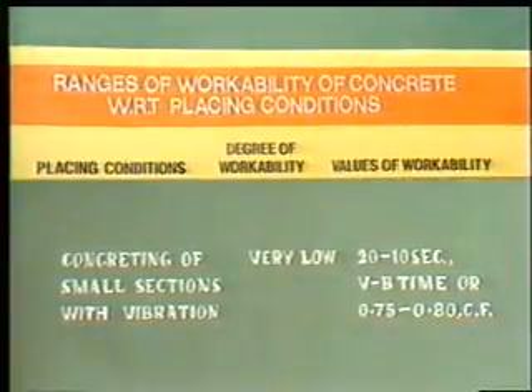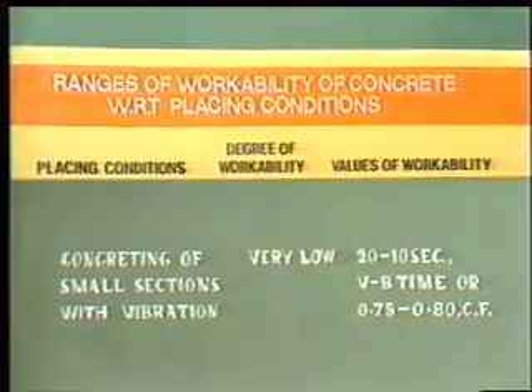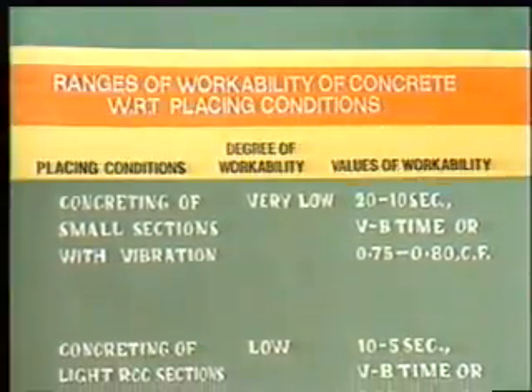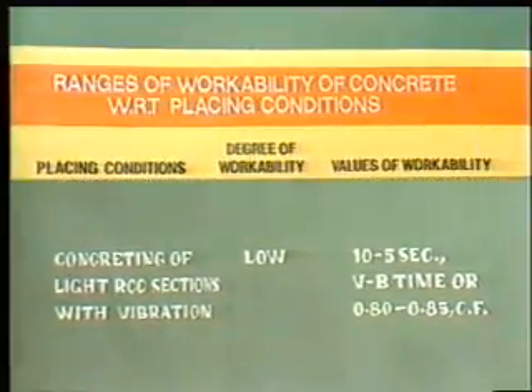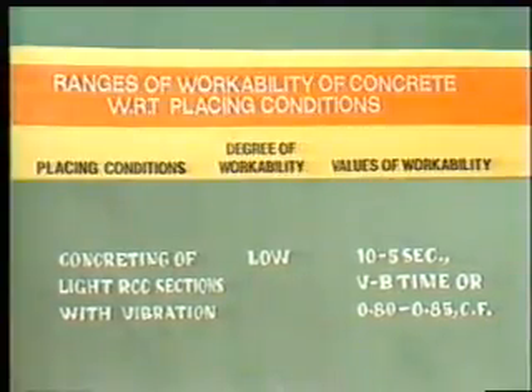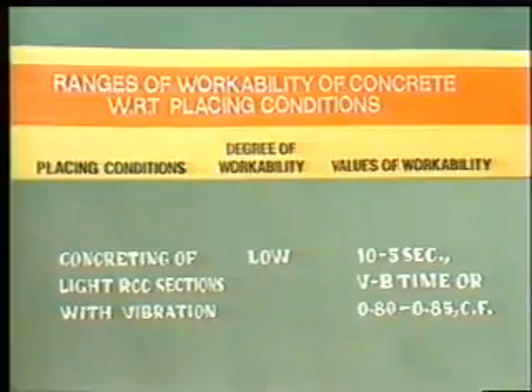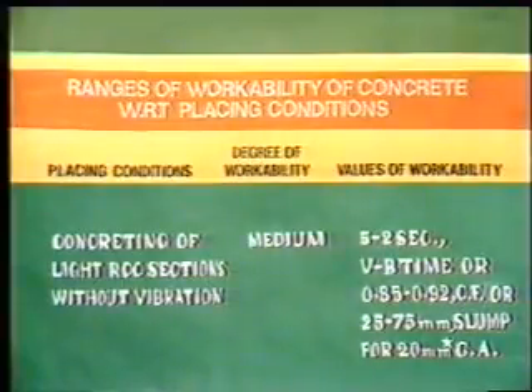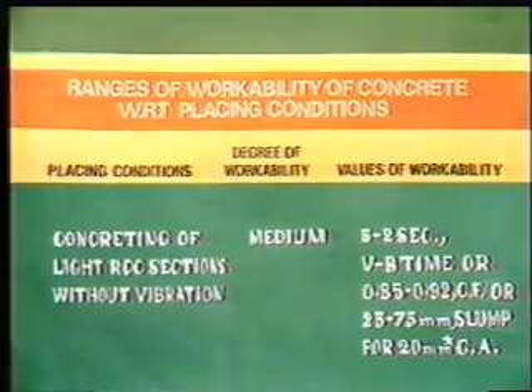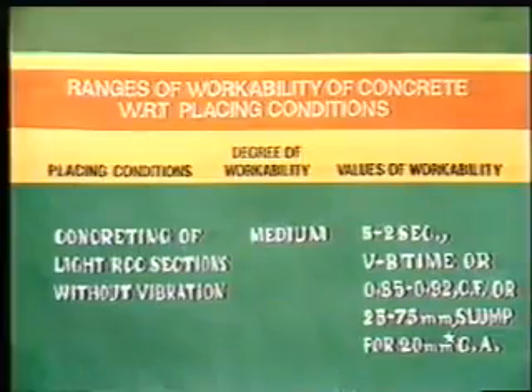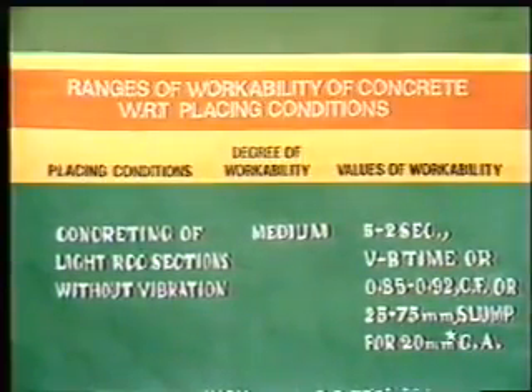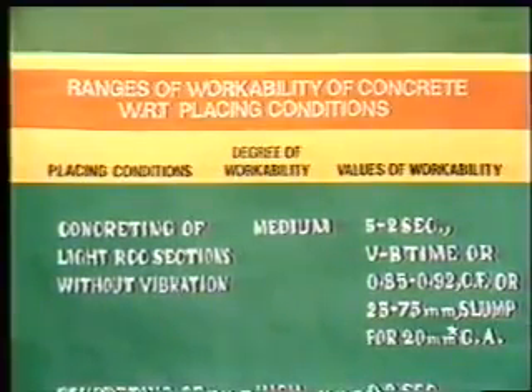Ranges of workability of concrete with respect to placing conditions. Concreting of small sections with vibration: workability very low, VB time 20 to 10 seconds, compacting factor 0.75 to 0.80. Concreting of light RCC section with vibration: workability low, VB time 10 to 5 seconds, compacting factor 0.80 to 0.85. Concreting of light RCC section without vibration: workability medium, VB time 5 to 2 seconds, compacting factor 0.85 to 0.92, slump 25 to 75 millimeter.